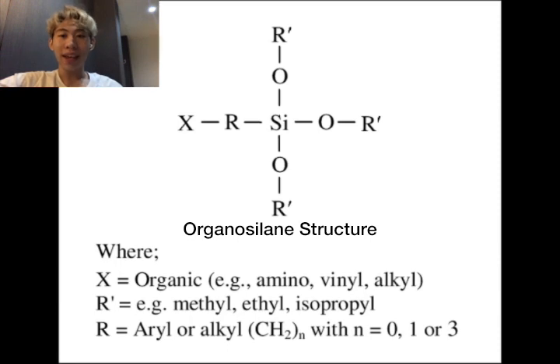Organosilanes have the capability to create siloxane surface layers, and these siloxane layers play a pivotal role in boosting the anti-corrosive efficiency of polymer and paint coatings, making them highly effective in preventing corrosion and enhancing their adhesion to the metal substrate. Siloxane possesses a unique mechanism of anti-corrosive action, making it invaluable in protecting metals from a variety of corrosive environments. The processes occur during the hydrolysis of organosilanes in aqueous solutions and their interaction with metal surfaces.